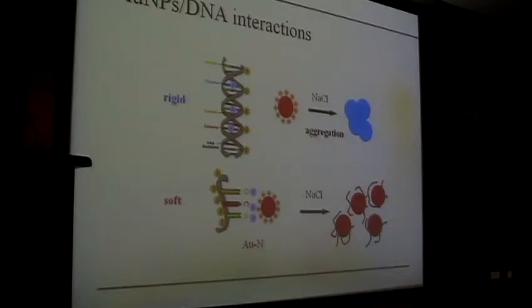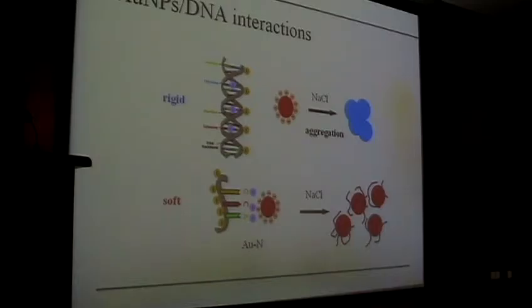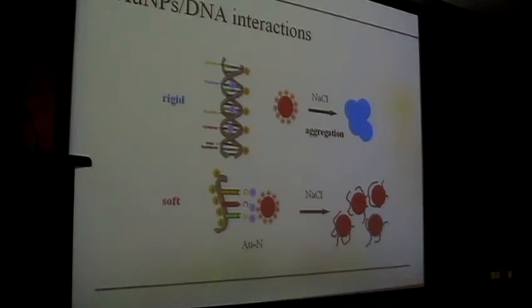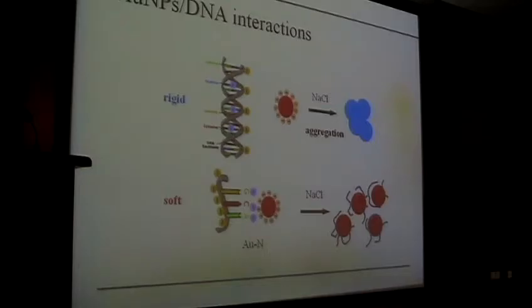Why? As you can see from this picture, DNA contains A, G, T, C — the four bases. All these bases have nitrogen atoms, and gold-nitrogen interactions have a relatively strong adsorption strength. In single-stranded DNA, AGTC is exposed, while in double-stranded DNA, A binds to T and G binds to C, exposing the phosphate backbone to the solution. So AGTC is buried inside, and cannot interact directly with gold nanoparticles.